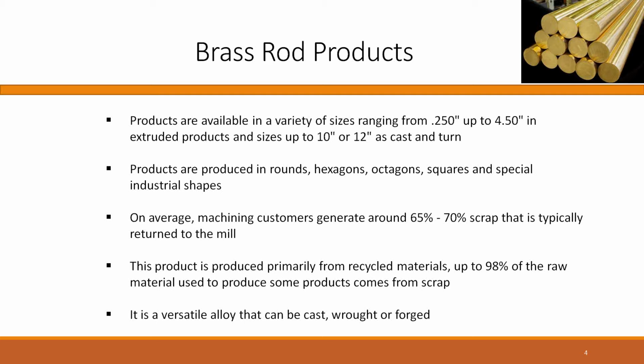In that case, that's where the adjustment needs to be made, because they may just be a copper zinc alloy, and then you've got to add lead, or you've got to add more zinc, or you've got to add copper because the alloy that came in has more zinc in it than what you need in your final mix. And then brass, because of its nature, can be cast, it can be hot extruded and cold drawn, it can be forged, it can be bent. It depends on the chemistry as to what the capability is of the final alloy and form that the customer needs in order to produce the products that they want to make.